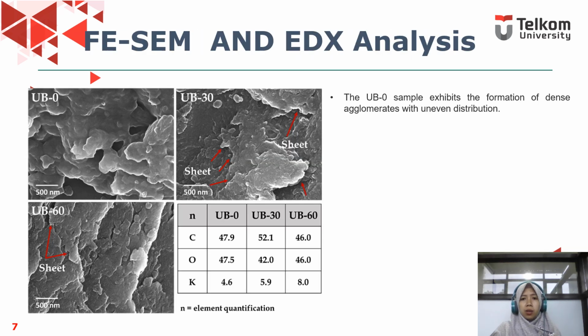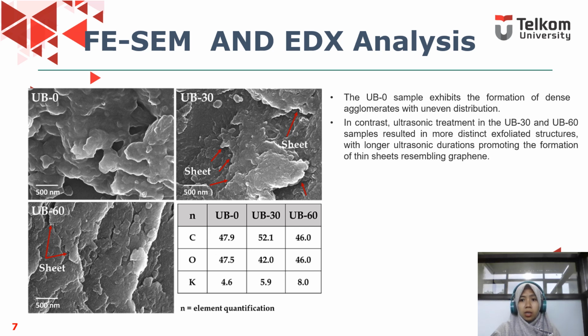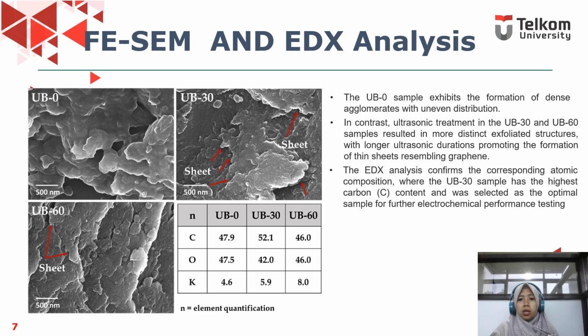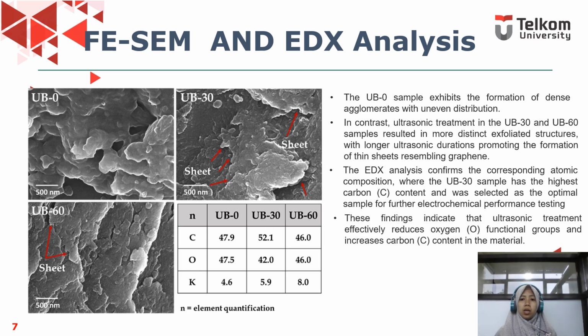Okay, this is FESEM and EDX analysis. The UB-0 samples exhibit the formation of dense agglomerates with uneven distribution. In contrast, ultrasonic treatment in the UB-30 and UB-60 sample resulted in more distinct exfoliated structure with a longer ultrasonic duration, promoting the formation of thin sheets resembling graphene. The EDX analysis confirmed the corresponding atomic composition where the UB-30 sample has the highest carbon content and was selected as the optimal sample for further electrochemical performance testing. This finding indicates that ultrasonic treatment effectively reduce oxygen functional groups and increase carbon content in the material.